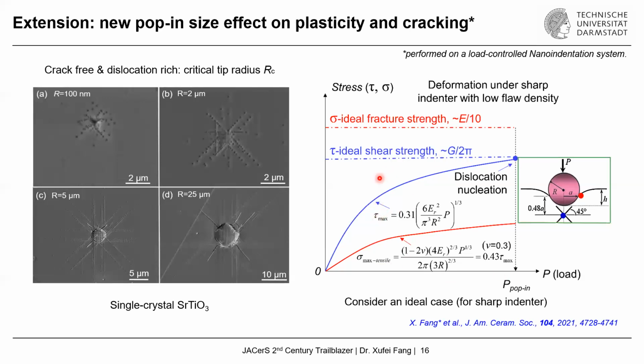And when we compare them to the theoretical fracture strengths and theoretical shear strengths, we realize that the applied maximum shear stress can easily achieve the theoretical shear strength to break the bonds and induce dislocation activities even before the material can induce the cracks. So this somehow explains why the very sharp indenter can generate dislocations without creating cracks, but we are still working on what is happening with the larger tip indenter, for the coexistence of cracking and plasticity.